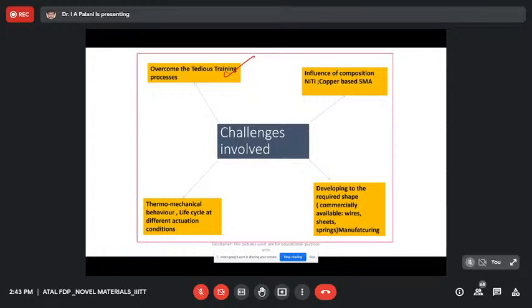Second thing is the influence of composition. Commercially, when we try to buy a shape memory alloy, we get either a nickel titanium material or a copper-based shape memory alloy. We don't really get copper-based ones, but nickel titanium is commercially available. So it is very difficult to investigate the influence of different compositions. We may feel that when we include intermetallics its properties may improve, or in some cases we may need to employ such structures for functional applications. Because of the limitation in usage of the material, it is difficult for us to proceed further. Such different attempts are available.